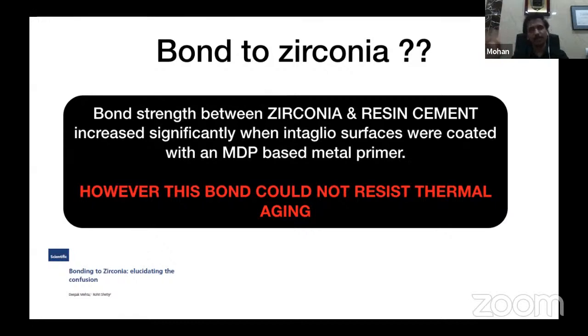Now zirconia, as I told you, is very, very problematic. See, from the beginning, zirconia could not bond to anything. That was the reason why the veneering of zirconia was stopped. If you ask any lab, they would directly give us only monolithic zirconia. That's why the aesthetic level with zirconia is coming down. Though today translucent blocks have come and also multi-layered blocks have come, there is always an issue with zirconia if not layered. So layered zirconia will fracture at the interface, but in a zirconia as such, if a crack is developing, that means it is 100% leading to fracture.